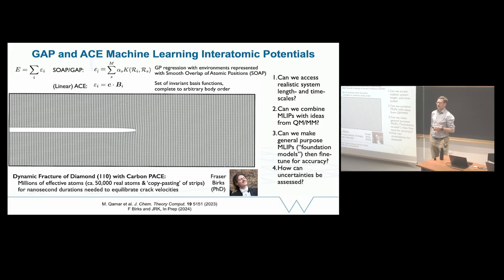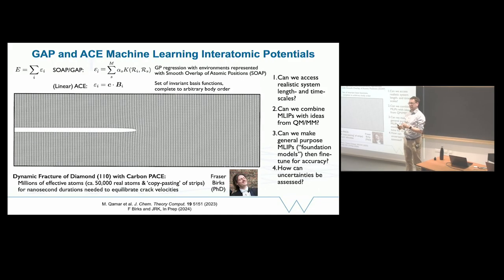You have the input for the Z direction. If we see here the XY direction, do you consider that it is periodic? Yes. So in these simulations, it's periodic and it's quite narrow, 1 or 2 lattice units. I'll show an example later on where, given the potentials, we can now go large in that third direction as well. With DFT, it was not possible to do anything other than this 2.5-dimensional simulation. But with potentials, we can make it large in the third direction as well.